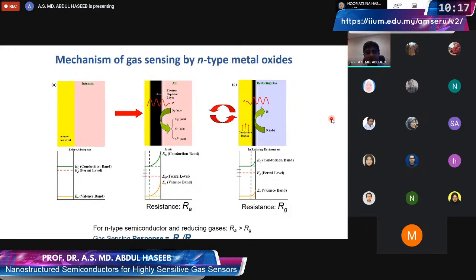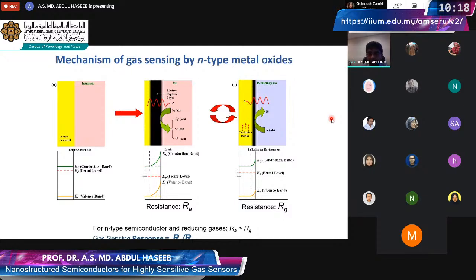And we now define the response of this material to the gas by using this ratio Ra over Rg. Now, this is greater than 1, as you can see, and it depends on the concentration of the reducing gas that is in contact with the N-type semiconductor. So if the gas concentration is high, then we have a higher value of this quantity.